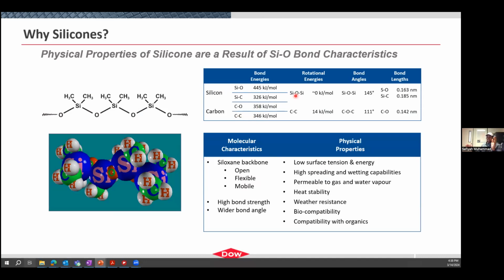We also take advantage of the geometry, right? If we look at the bond angles of that siloxane bond, you see that they generate much wider angles than your carbon-based polymers. And so it's mainly these two properties which we utilize in order to get certain characteristics out of the polymers. With the bond angle being so wide, you get a much more open, flexible, mobile backbone, which translates into properties such as low surface tension and energy. It allows us to take advantage of better wetting properties, right? Higher spreadability.